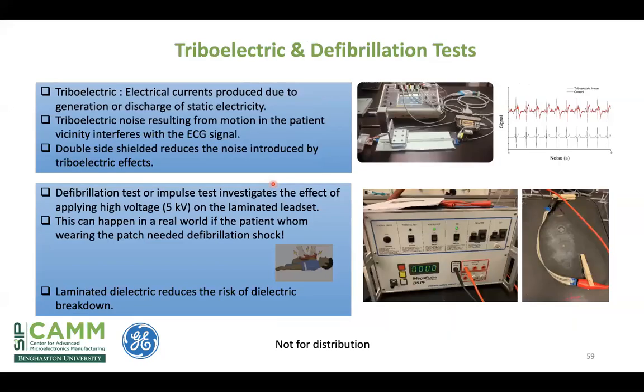And so additional tests that we performed involved this triboelectric test, and you can see the triboelectric effect here shown very clearly in this ECG pattern, which has been noised by the presence of movement of a hospital gown or an article of clothing, and with proper circuitry and proper isolation in our printed coax, we were able, in fact, to eliminate this noise. In addition, if the patient were needed to be defibrillated, this is also a test that we can perform. This is a device that we have here. It literally applies the high voltage, 5 kilovolts, to this printed structure.